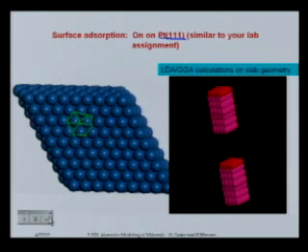So if you want to study the adsorption of something like hydrogen or oxygen, again, you build a lattice model. Then you have to do density functional theory calculations to parameterize it, and I think you've done that now in the lab. Because this is a surface, you would set up a slab geometry. So you essentially would take a few layers of platinum and then put stuff on the surface to adsorb it. And you put a range of vacuum above that and do the DFT calculations.